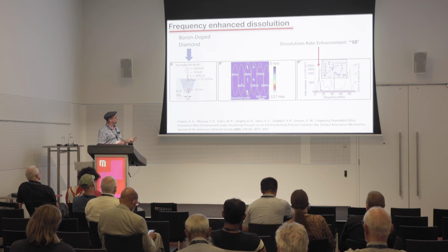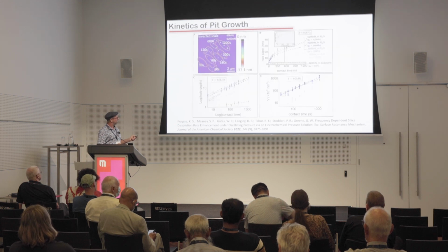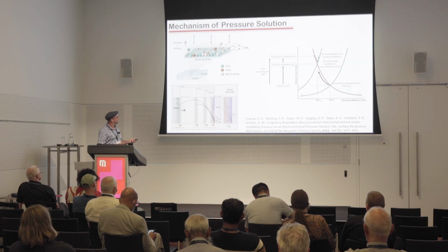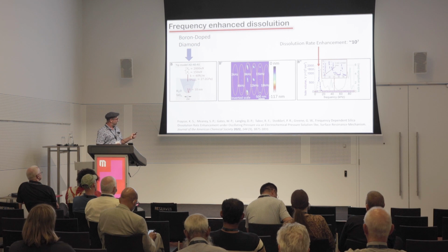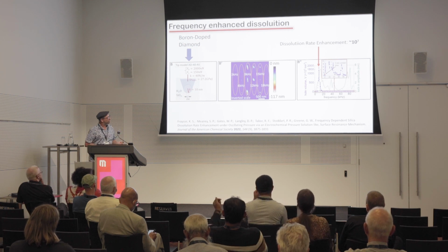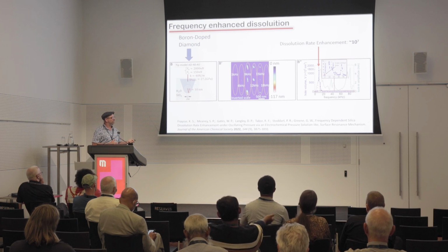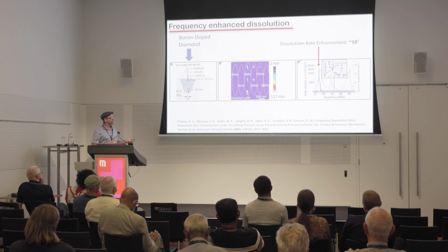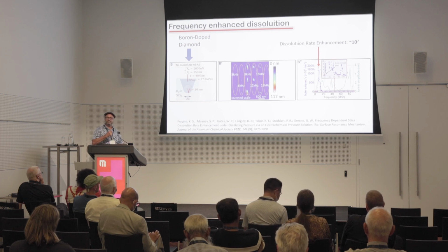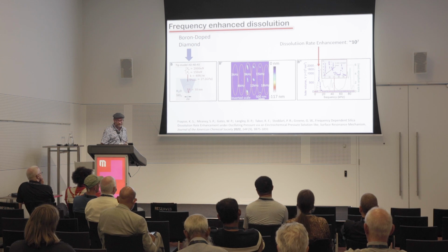Then at 6 kilohertz, they get a little bigger. And at 9 kilohertz, they get massively big. And then as you increase the frequency again, they start to get smaller. Now, when you plot essentially the whole volume as a function of the frequency, you can see that the frequency dependence is very, very sharp. So this indicates to us that what we're looking at is a type of resonance phenomenon.